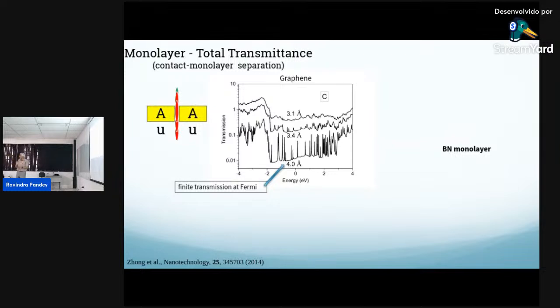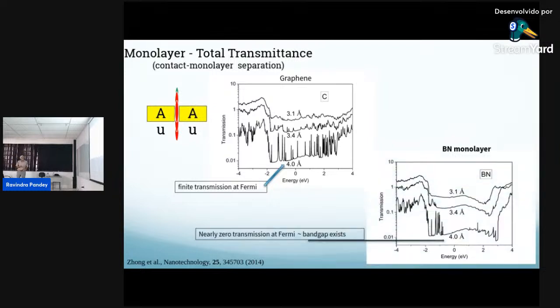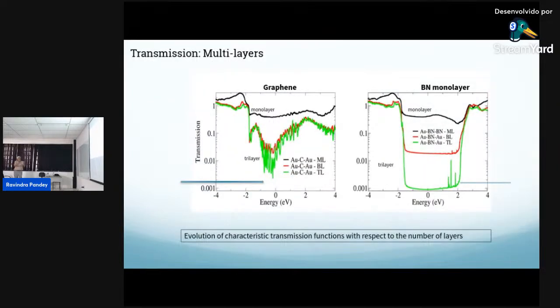It sort of makes sense. Let's see what happens to boron nitride. We started from here, finite transmission at 0, comes down, and you can see at 4 angstrom it just behaves like a semiconductor. It's a very, very small transmission. Then we go to the other spectrum. So this is simply where we played around with the contact material distance.